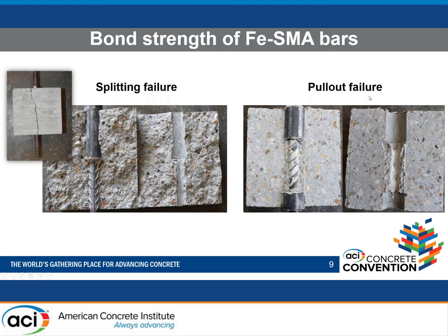For the pull-out failure, obviously, we needed to cut the specimen in order to see what happened inside. And clearly, you can see that the concrete between the ribs has been sheared off. Like here we have a smooth surface as compared to this surface, and we have concrete in between the ribs of the E-bar.